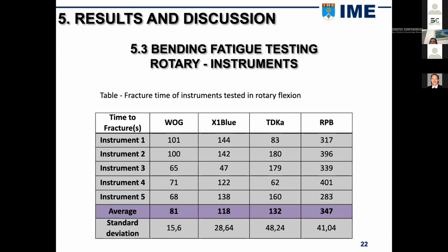This table shows the fracture time of the instrument samples tested in the rotary bending test. There was an inverse relationship between RA and valley values and fracture time. The RA value alone should not be considered as a parameter to predict a shorter or longer time to fracture resistance. It is interesting to relate it to other parameters, such as valley depth.